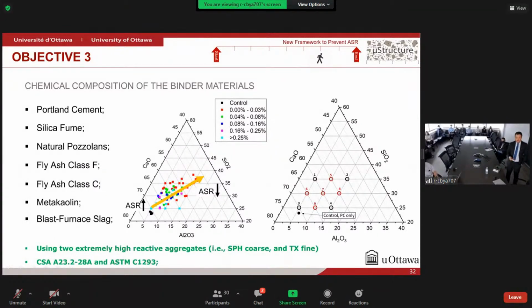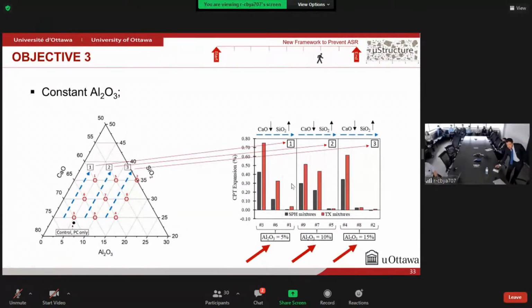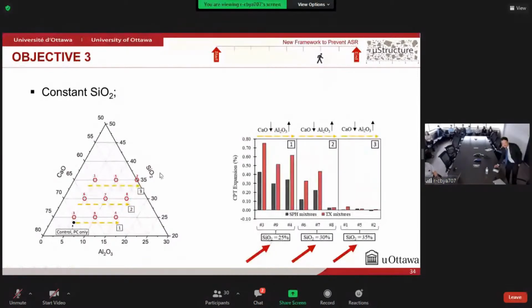For example, if we follow these blue arrows here, as indicated, we will have a constant amount of aluminum for each of them here. But if we follow their indication, we will have a decrease in the amount of calcium, an increase in the amount of silica, and at the end, we will have a huge decrease in the final expansion of the concrete. But now, if we follow the fixing of the silica amount here and following the arrows, we can see that decreasing the calcium, we have an increase in the amount of aluminum, and we also have a decrease in the final expansion, but not as clear as before once we fixed silica, indicating that the amount of silica in the binder materials seems to be more important to mitigate and to prevent the development of ASR.